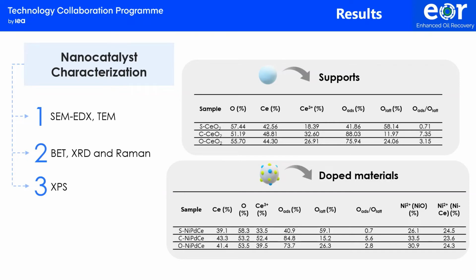The oxygen results corroborate this hypothesis. The content of lattice oxygen ascribed to the surface was modified after the doping processes. In all samples, the lattice oxygen increases in the same increasing order as the ceria 3+ ions.